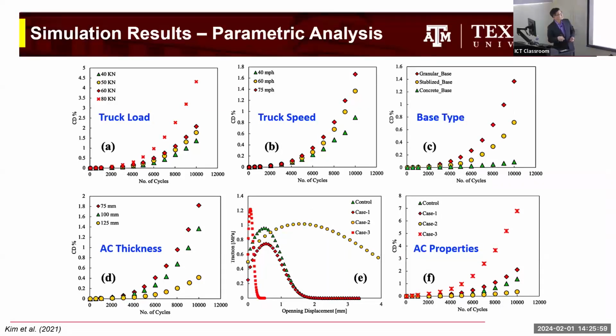And we can do kind of parametric analysis. What if I change truck load or truck speed, or change the base material, like a softer granular base or a stiffer concrete base under the asphalt layer, or the thickness of AC, or the property of AC, like using rejuvenators or polymer modifiers or waxes, different kinds of things coming in, then AC property can affect your pavement performance. As you can see, like percent damage as a function of the number of loading cycles. So we can see that. We can do good parametric analysis and look at the effect of individual design variables.